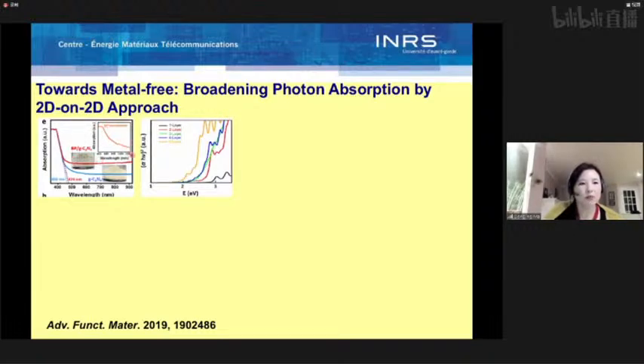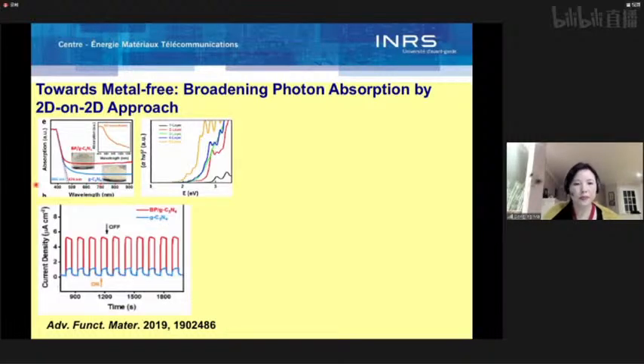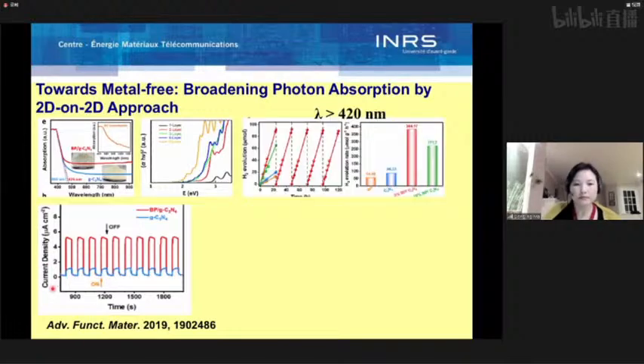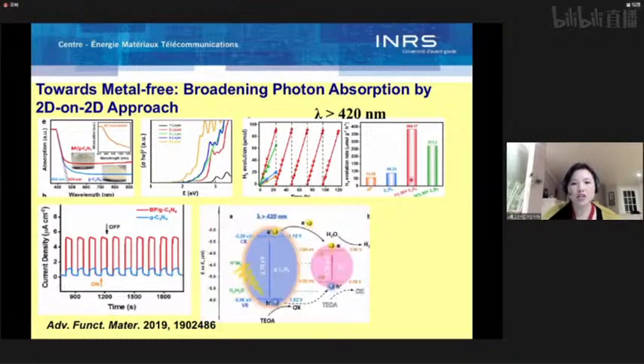You can see BP can absorb up to the near-infrared range. So we combine BP with C3N4 for the nanohybrid. We get improved light absorption. And with solar simulator irradiation, you can see photocurrent is largely enhanced as compared to plain C3N4. Under visible light irradiation, the hydrogen evolution is largely increased. For 3% of BP on C3N4, the hydrogen generation rate is about several times higher than that of BP and that of C3N4. Because in this system, BP only accounts for 3%, basically most photons are absorbed by C3N4.